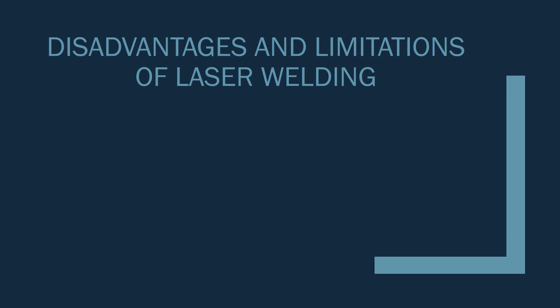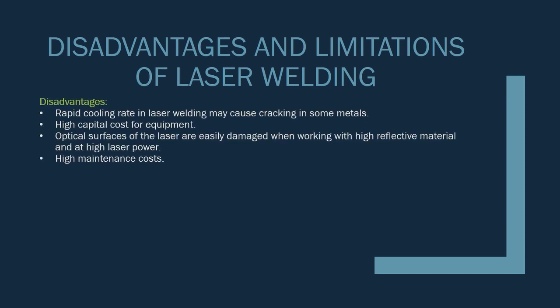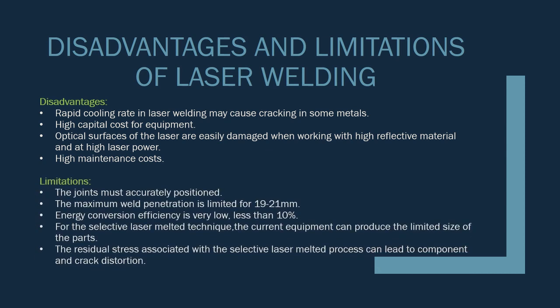Disadvantages and limitations of laser welding. For disadvantages, the rapid cooling rate in laser welding may cause cracking in some metals. High capital cost for equipment. The optical surface of the laser is easily damaged when working with high reflective material and at high laser power. It also has a high maintenance cost. For limitations, the joint must be accurately positioned. The maximum weld penetration is limited to 19 to 21 mm. Energy conversion efficiency is very low, which is less than 10%. For the selective laser melting technique, the current equipment can produce only a limited size of part. The residual stress associated with the selective laser melting process can lead to component and crack distortion.